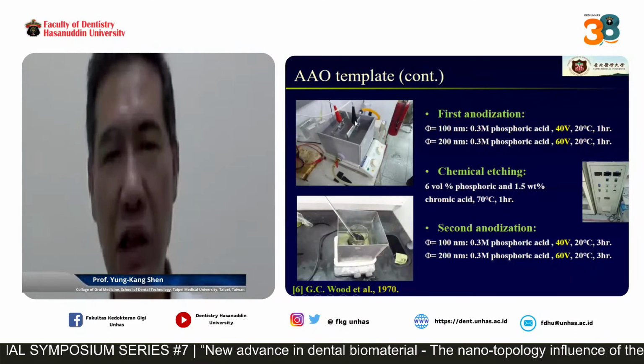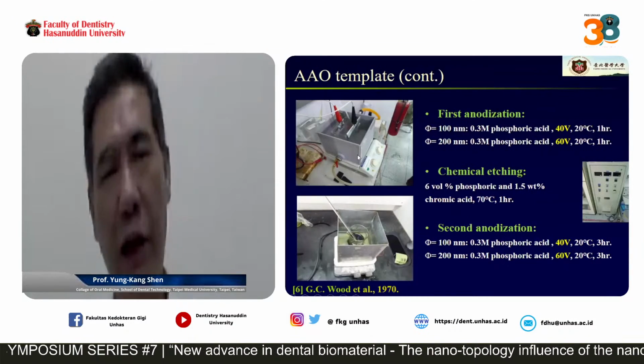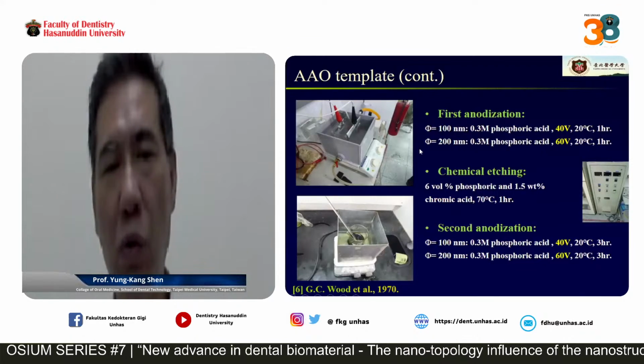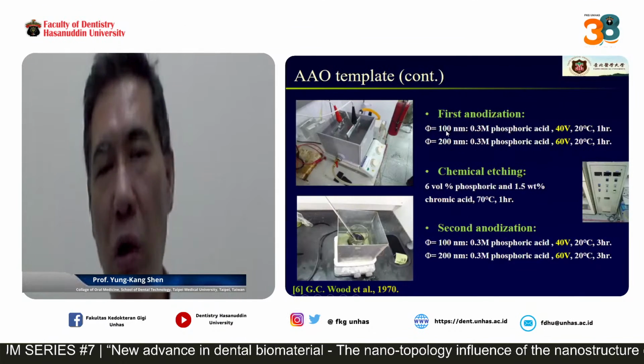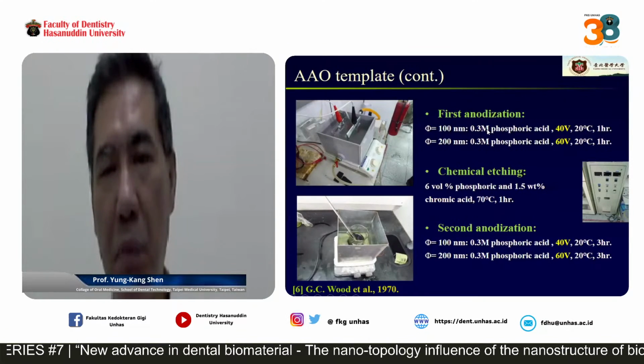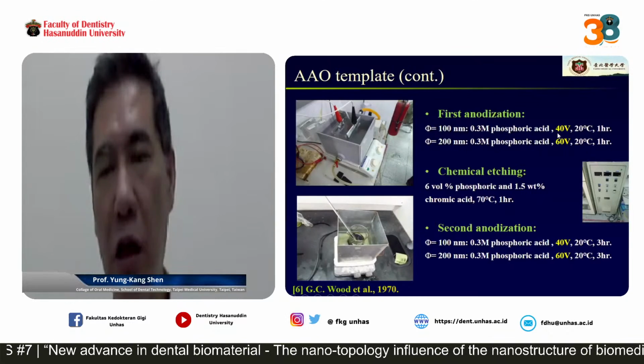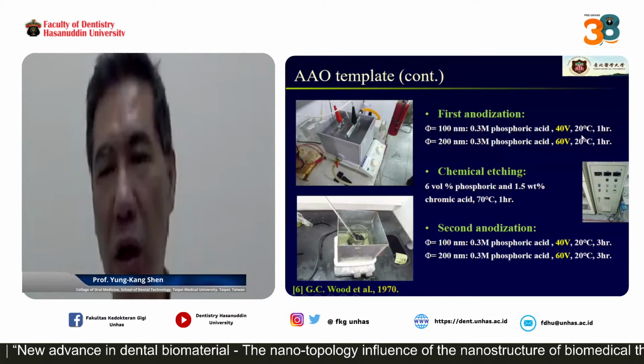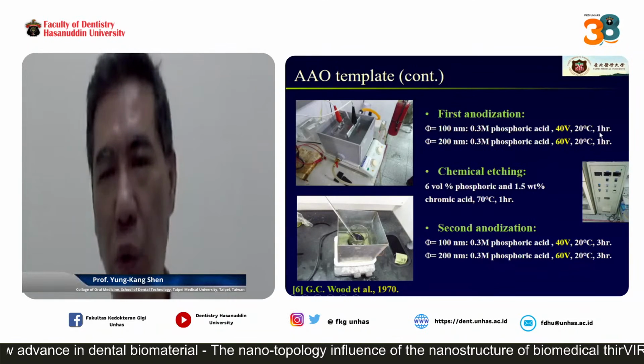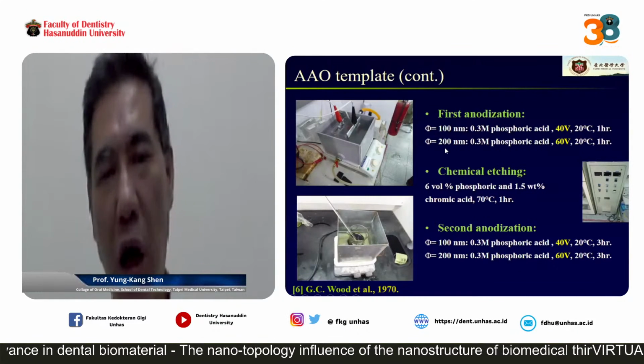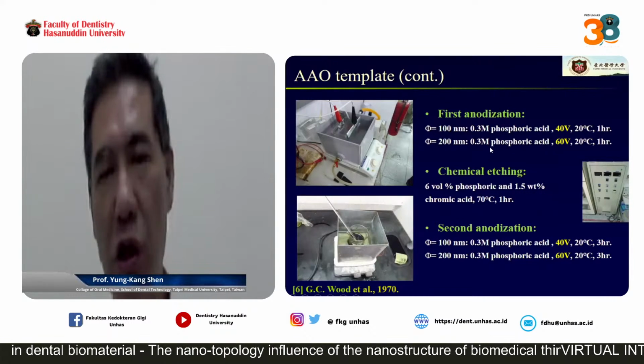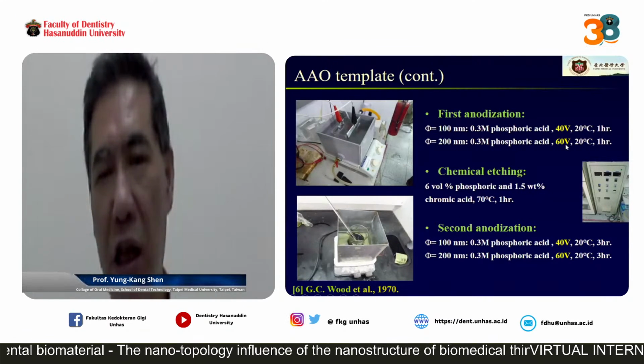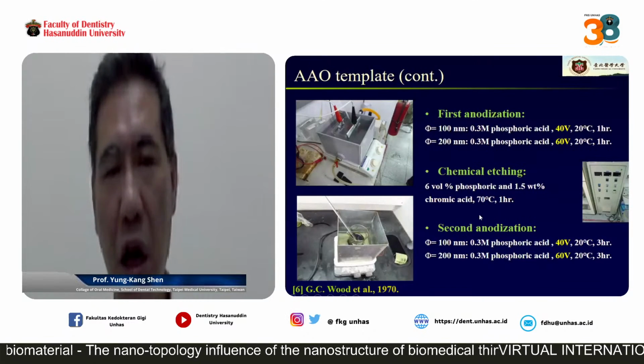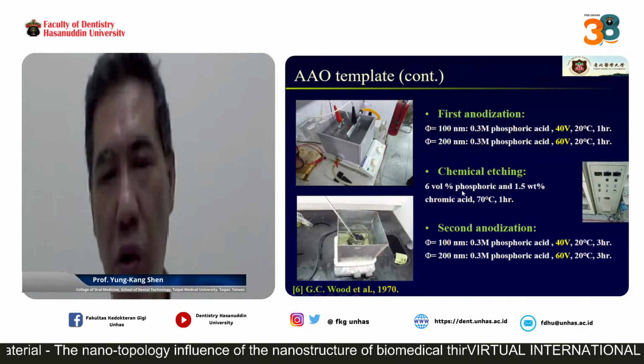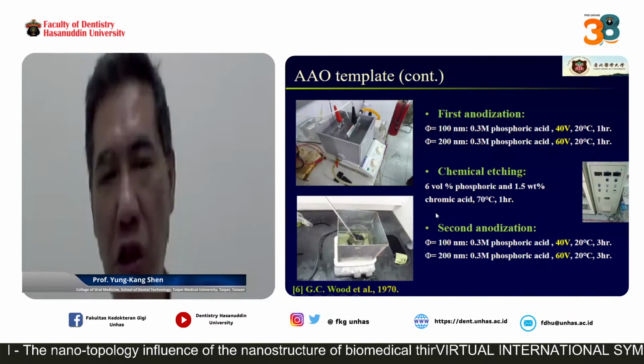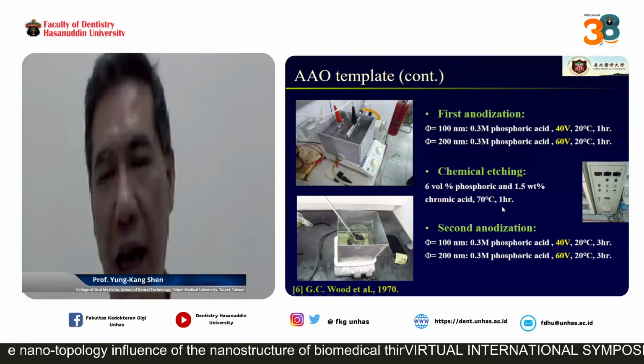And also you can see this is the anodization cell. For the first anodization, when we want to make the 100 nano hole, we use 0.3 molar phosphoric acid. The voltage is 40 volts, at 20 degrees C and 1 hour. If I want to make a 200 nano hole, I must use 0.3 molar phosphoric acid and 60 volts at 20 degrees C and 1 hour. For the chemical etching, we use 6 volume percent phosphoric acid and 1.5 weight percent chromic acid for 70 degrees C and 1 hour.